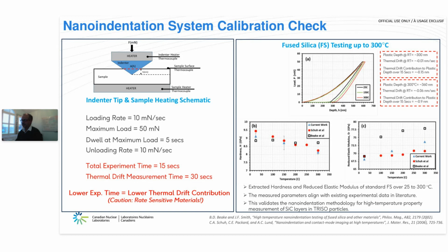So basically, we are getting similar trends as in the literature, and the right ballpark for hardness and the reduced modulus on the standard specimens. We deemed ourselves ready to move on to actual testing on silicon carbide coating and the TRISO fuel particles.